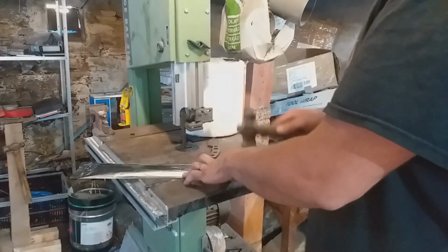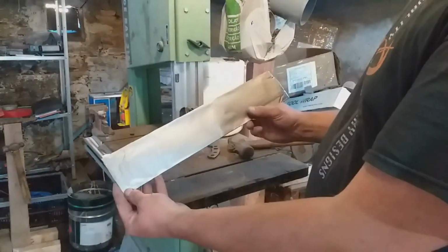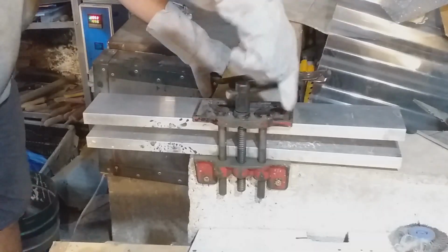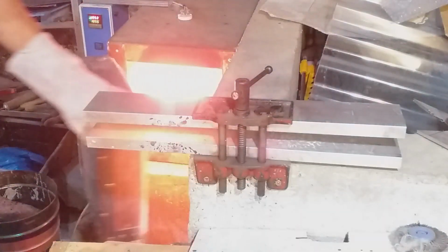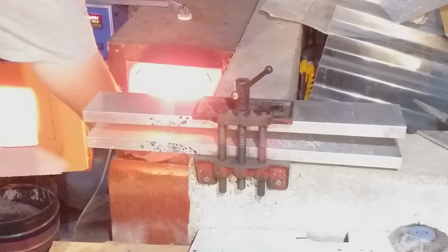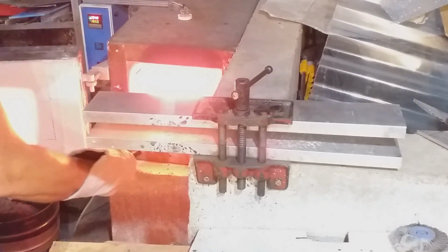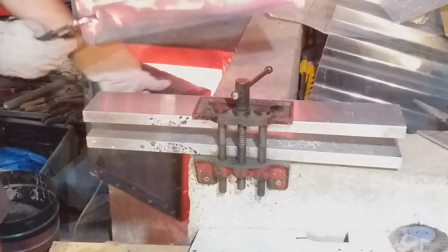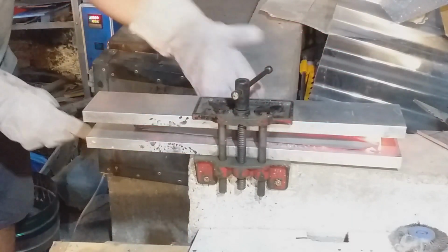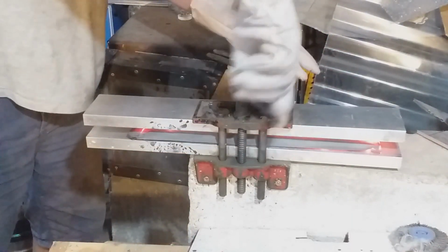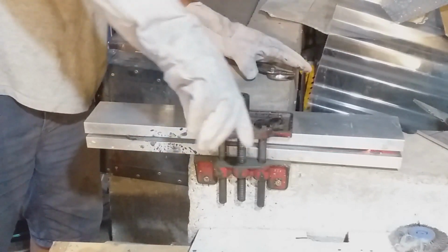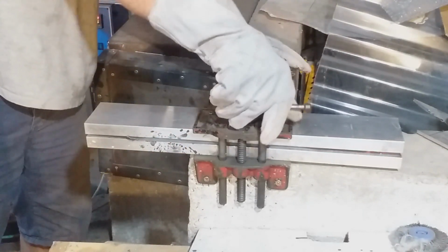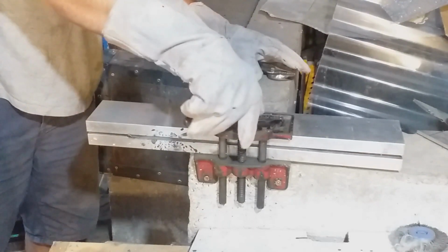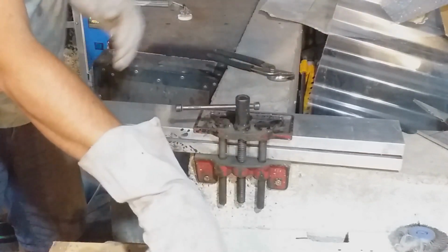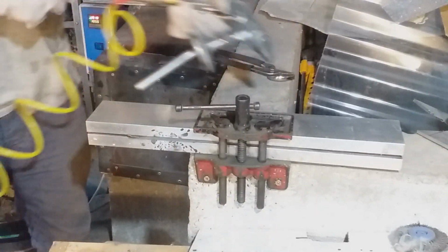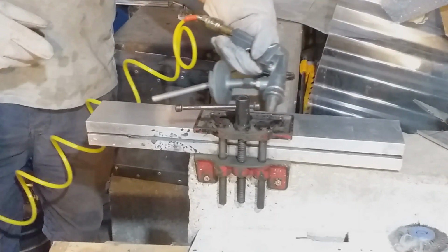Once the steel is soaked at the 1050 degree temperature for a set period of time, it then comes out and is put in between two large aluminium plates and cooled with forced air from our air compressor. This is an air hardening steel, as opposed to dipping into oil like you would do with some traditional steels. This one hardens purely by cooling down in air, so it's a more gradual process than dunking it into oil or water, which leaves a more guaranteed heat treatment result and a straighter blade at the end of it.